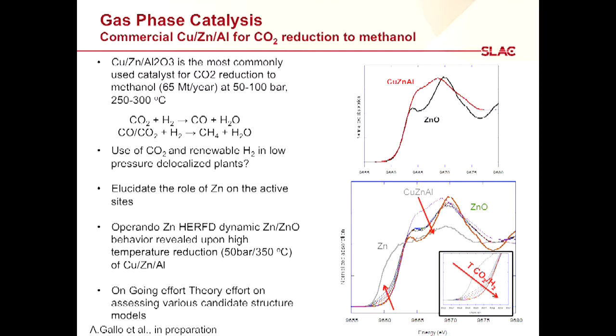And here we try to do a preliminary study to see how the copper and zinc X-ray absorption edges behave under realistic conditions and how they change when we change the temperature in order to promote those reactions. And here we have some information on the zinc versus zinc oxide behavior at different temperatures and different pressures relevant to CO2. This is an ongoing effort that doesn't only need experimental observations, right?